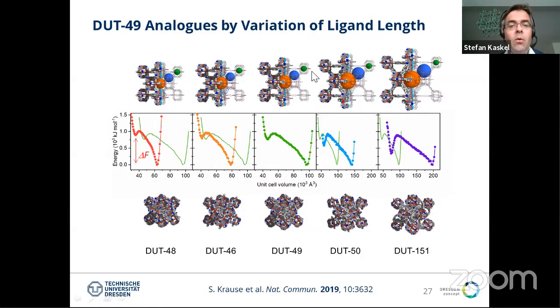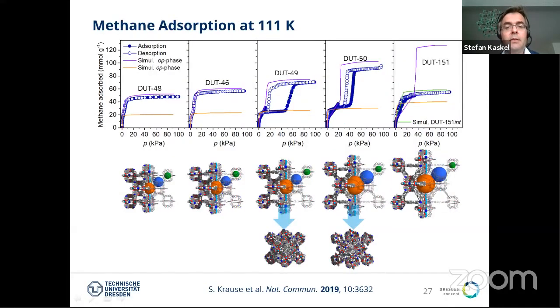Jack Evans calculated all the energy profiles for these type of materials, and all of them show a bistable profile. Here, the green curve is always the curve for the original material DUT 49. And it is compared here. And we see that the main differences between the different elongated linkers are basically in the difference of the free energy between the global and the local minimum. So this is getting closer and closer. This is an important point. And another important point is also that the volume change between the CP and the OP form is systematically changing here.